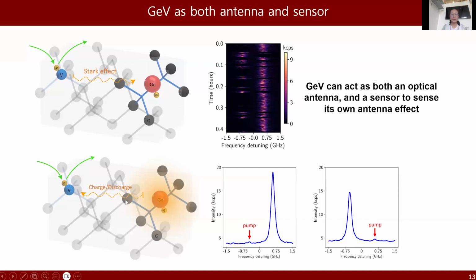To summarize, the near field generated by GeV can cause a charge cycling of this nearby vacancy. The charge cycling of this nearby vacancy can have a back action on the GeV itself, inducing a Stark shift to the GeV's ZPL. In other words, the GeV can also be used as a sensor to sense its own antenna effect, and we can study this near field enhancement by observing the GeV's PLE spectrum, the ZPL.